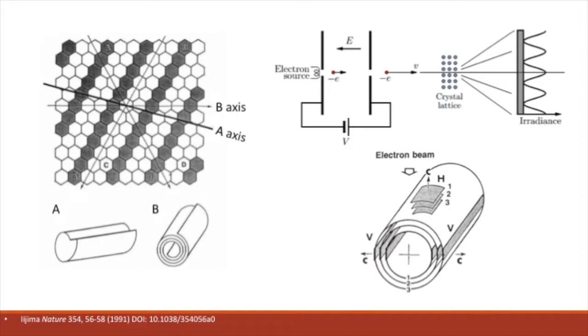Since the shape of nanotubes are symmetrical, Iijima noted that if you fire the electron beam at the top of a nanotube and out through the bottom, you can determine which orientation that they are in based on the number of diffraction patterns that are present. For example, since the end-to-end orientation will have the same atomic arrangement at the top and bottom, only a single diffraction pattern will be produced. However, if the tubes are in the staggered orientation, then the atomic geometries are different for the top and bottom of the tubes. Therefore, you should observe 2 separate diffraction patterns.